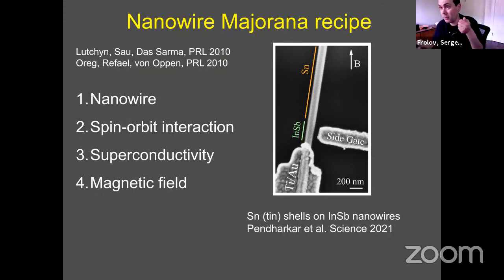So you need a nanowire, which is a one-dimensional system, like Kitaev's. Then you need to put superconductivity in it, like Kitaev did. And this you do literally by putting a superconductor, like aluminum or niobium, a simple superconductor, on top of your nanowire. That's how you introduce superconductivity, by the proximity effect, it's called. Then you need spinless fermions. You don't have spinless fermions, but you can spin polarize the electrons in a nanowire by a magnetic field. So you have a magnetic field.